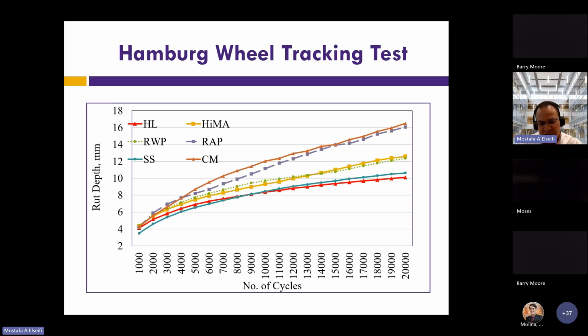And these are the different rut curves. You can see that most of the mixes performed in region 2 of the creep curve, so they did not get to the tertiary region. However, you can see that the control mix and the RAP had higher rutting than the other mixes. Again, the RAP was kind of a surprise for us, but it's possible that this RAP source had polymer sources in it, or it had some damage during field utilization. Also, the RAP content that we use is only 7%. So it's possible that at this low content, you don't see a very significant drop in rutting when you use RAP.